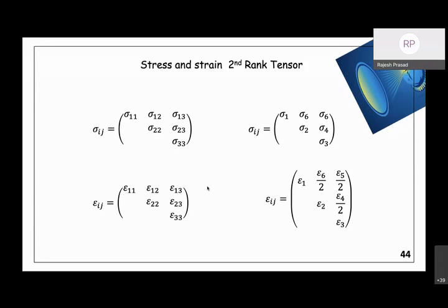But these considerations which I am showing will strictly work only for a pure single crystal. For polycrystalline material, one has to take the polycrystal averages. In which case, the polycrystal, if it is not textured, may behave isotropically. But again, if the polycrystal is textured, the anisotropy will come. But then the anisotropy will be a function both of the anisotropy of the crystal and the anisotropy of texture orientation. It will not be just the pure crystalline anisotropy. And in a totally random orientation of crystals in a polycrystal, the crystalline anisotropy will be totally washed out, and the material can be considered isotropic, which is what usually is done.